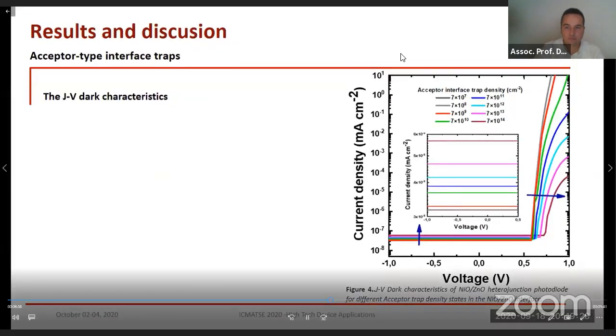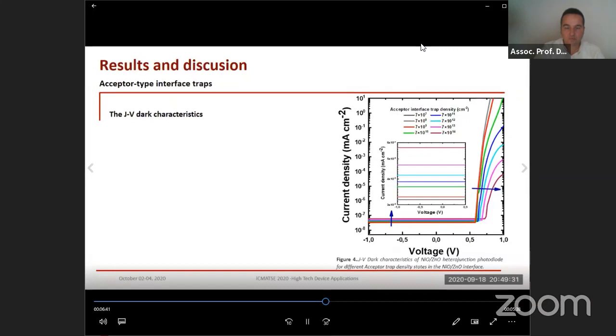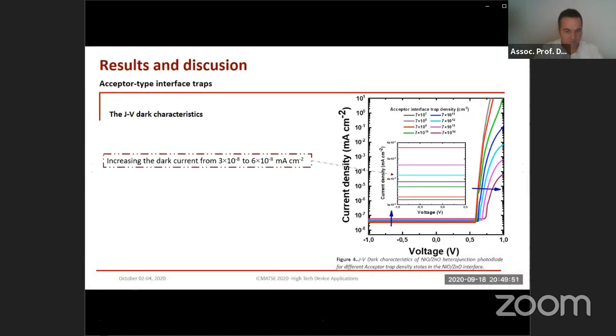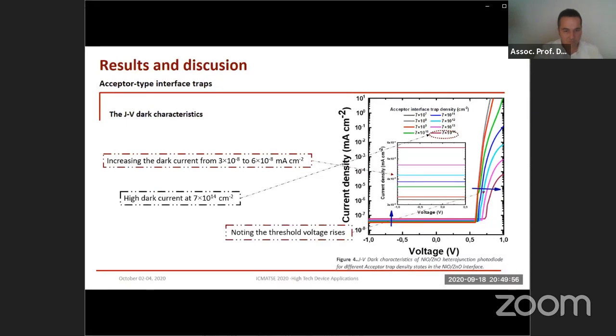Let us look at the first case. The first case was studying the effect of acceptor states on the photodiode performance. Conditions: negligible donor density. The value of the acceptor trap density was varied from 10^7 to 10^14. By increasing acceptor traps, the dark current rises highly at 7x10^14, with the threshold voltage rising as well. A low dark current density has been achieved at low acceptor trap density, which is the best choice for low